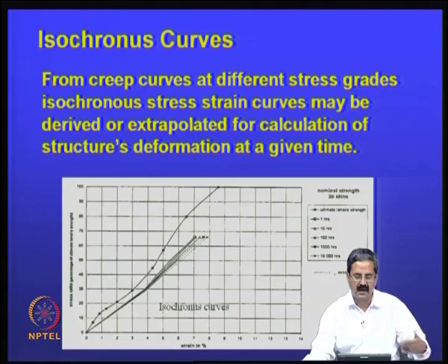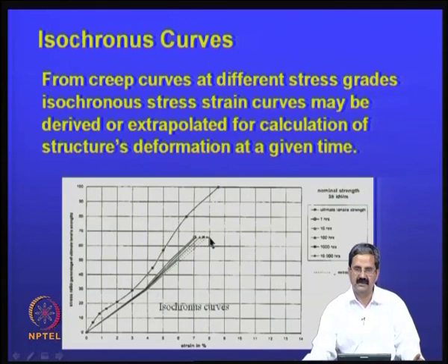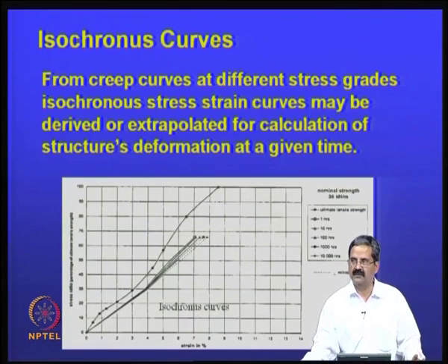For example, if the tensile strength could be 35 kilonewtons per meter, and you want it to work for about, say, 50 years, you may have to use a creep factor of 1.3 or 1.5 or whatever. So, it depends on this type of testing.